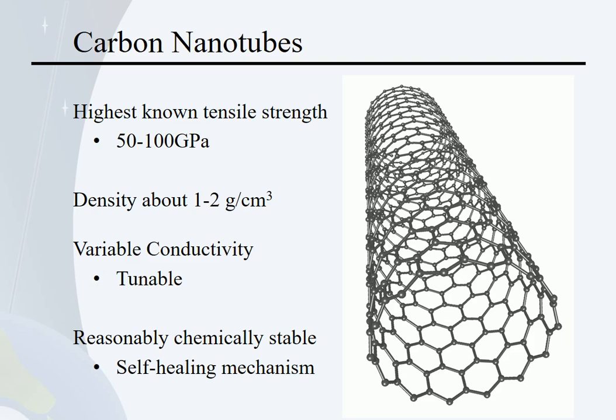They do have one weakness, though, chemically speaking, and that's ozone and oxidation. While they don't start oxidizing or start burning until those high temperatures we just mentioned, they also don't have a stable oxide. Now, what this means is, as nanotubes oxidize, they lose mass and they gain defects. And this isn't true for all materials. Aluminum is a classic counterexample. It too oxidizes, and in the case of aluminum, incredibly readily. But that oxide layer is a stable solid and prevents further oxidation of the bulk structure.